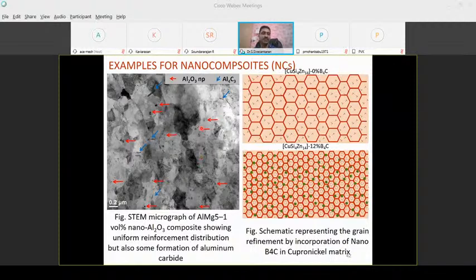For example, you see this is a metal matrix composite, an aluminum magnesium alloy. These are all grains, around 200 nanometers. And you see the black dot, the red arrow indicates the nanoparticle, aluminum oxide, and the blue color indicates the fiber form, aluminum carbide nanofiber. It is one example of a metal matrix composite. This is the image obtained from the transmission electron microscope.